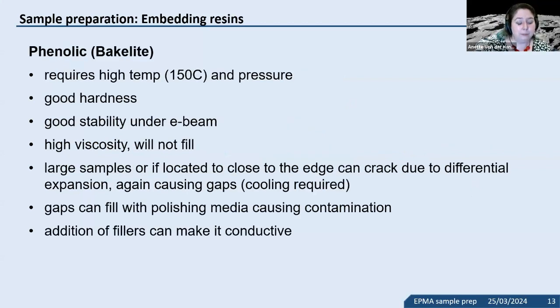What you often see in old times, but also in materials science, are phenolic resins, like Bakelite. They have good hardness and stability, but can be problematic too, because samples can crack, or you can create gaps that cause contamination. One useful thing with phenolics is that you can add a filler that makes them conductive. So if you have a non-conductive material, you want to have it either coated, because the epoxy will not be conductive, or embedded in a mounting media that is also conductive.